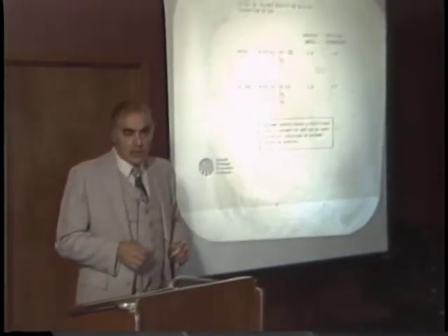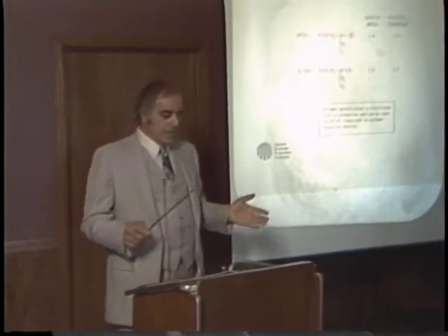This is a difficult thing to demonstrate, but we chose this system because there is a similarity in structures between the two materials. In this instance, chlorine replaces a methyl group on a 1,2 polybutylene glycol type of polymer. The density of this system is about 40% higher than this. And as you can see, if we take a permeation of 1 for this, then this has 2.7 times the permeability. Now, some may argue that chlorine affects the polarity of the system. We feel that they're about the same polarity, so that we do not feel that the polarity effects were there.